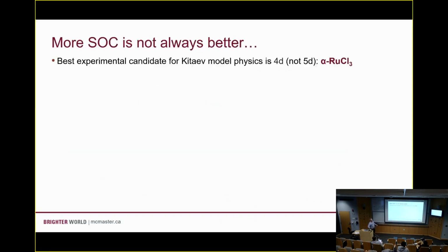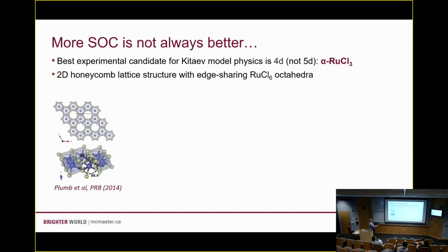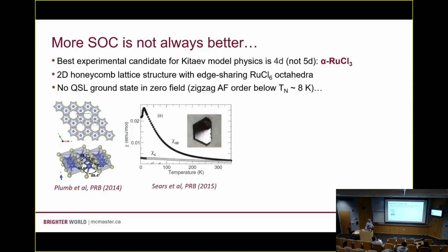But one of the lessons that came out of more work on this is that more spin-orbit coupling isn't always better. The best of these experimental candidates that we have for Kitaev model physics isn't actually these honeycomb iridates. It's a 4d transition metal compound, alpha ruthenium chloride. I'm going to cite the seminal work of Kim and Kee from 2016 here. This is another edge-sharing octahedral crystal structure, now based on a 4d transition metal instead of a 5d transition metal. It's not a quantum spin liquid.